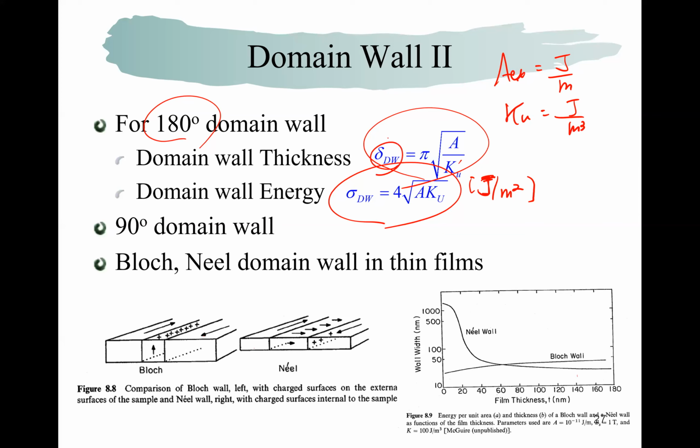So to obtain the length, what you can do is divide these two terms and take the root. Then you get the length scale. Okay. And how about the energy? We need to multiply these two, and if we multiply these two, we have this result. So we get joule per meter square, the surface energy term. This is another, the most simple, estimation of this energy form.